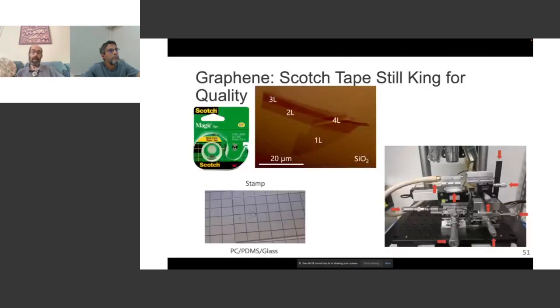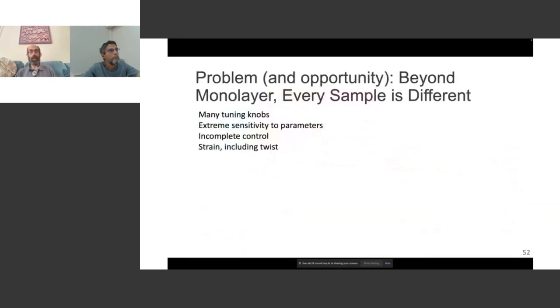So this is how we've been doing the stacking. We did the stacking on that sample. You can see there are many manual manipulators and two motorized manipulators for getting very fine control of bringing the layers together and the twist angle. But now a colleague, Andy Mannix in materials science at Stanford, and I have built a system to do such stacking in vacuum with much more exquisite control. This builds on work that Andy did in his postdoc at Chicago with Jiwoong Park. And I'm hopeful that that's going to allow us to control these sorts of things.